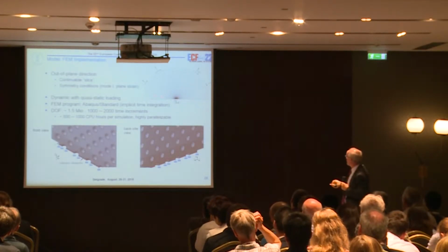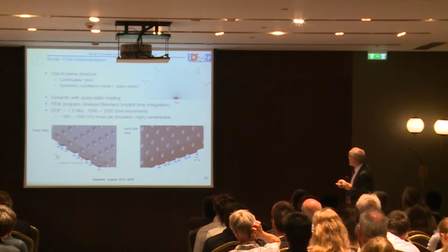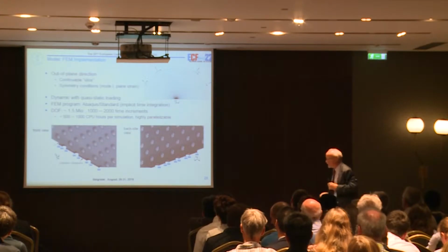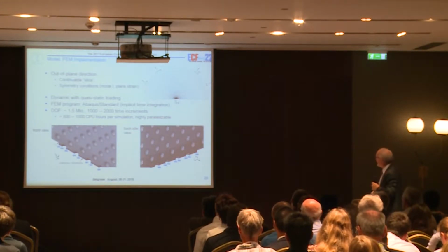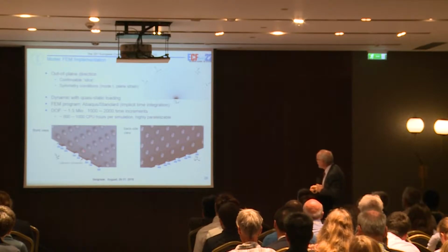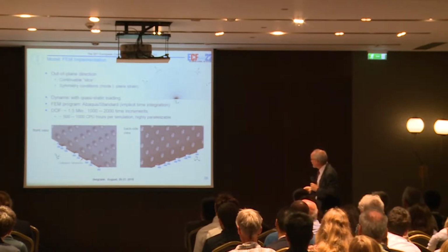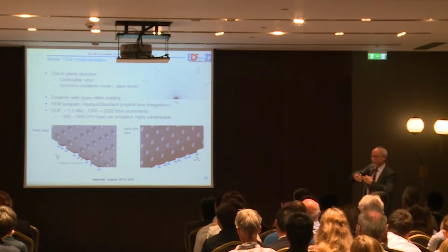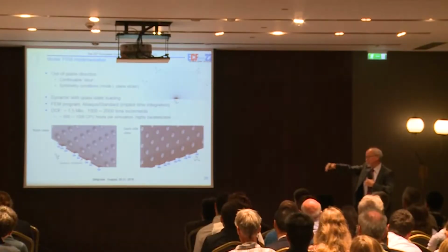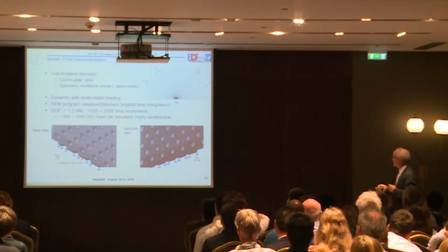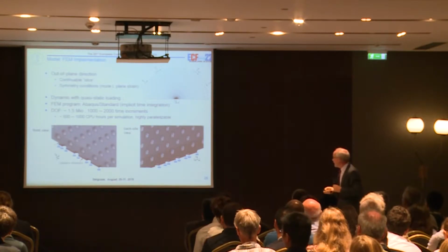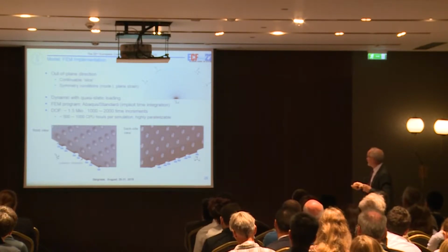Here you see the outer mesh, and very far inside, which you cannot plot, we have our discrete process zone structure. It is a front view. Here you see the individual voids and the cohesive elements, and this is the backside view. We simulate only a slice, a periodic slice, to simulate an infinite width of the crack front in mode I plane strain.